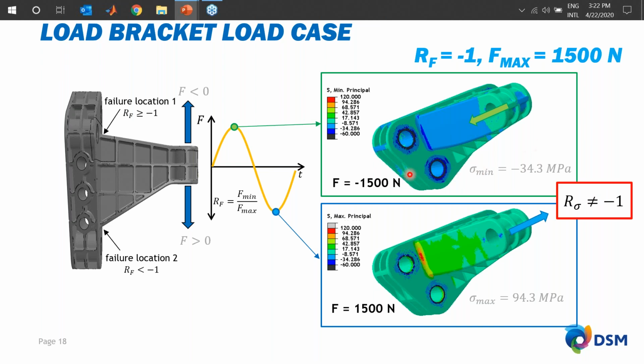So that means that we apply a certain force ratio which is equal to -1, but the local stress ratio is far away from -1. It's actually only -0.4. So you really have to take into account the local stress ratio to do proper fatigue calculations, simply because the local R value is really affecting the lifetime of that response.